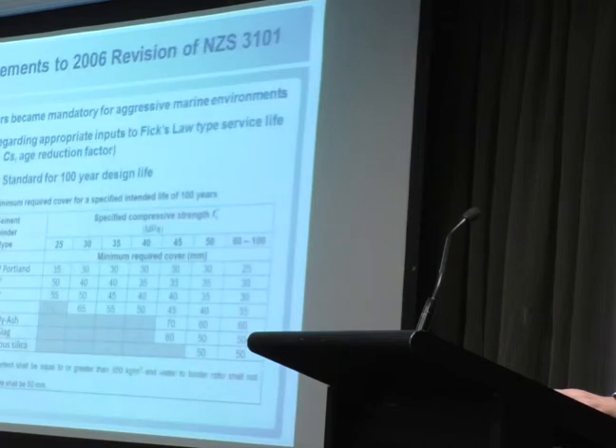And as a result of this work, the New Zealand code was revised. The main changes were making it mandatory to use a supplementary cementitious material for all concrete that was going into the aggressive C zone, so concrete that was going to get splashed or potentially splashed by direct wave action, or was physically in brackish water. And also a table was included for 100-year design life, which is shown there. And guidance was provided in the standards as to appropriate inputs to Fick's law models if you wanted to choose that alternative.